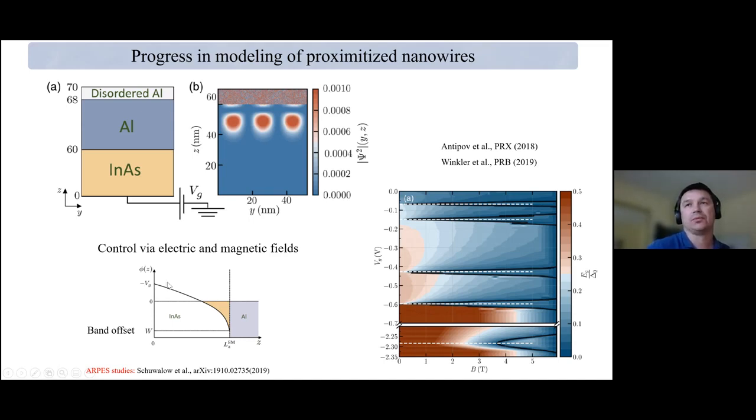And it's an important consideration because it tells you which fields one should expect to get into the topological phase, and it highlights another point, that there is a renormalization in these interfacial Hamiltonians. And this renormalization comes because the electron wave function spends some time, has some weight, in the superconductor and semiconductor. So that's essentially the origin for this renormalization.